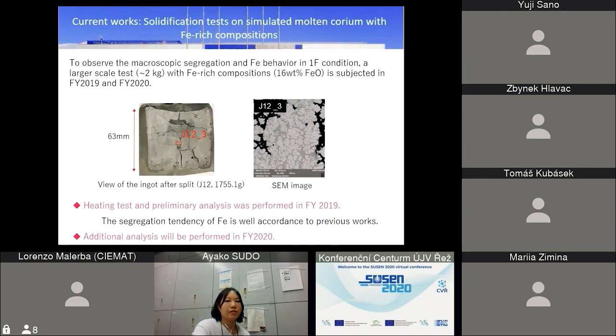Okay, next I will introduce current work: a solidification test on simulated molten corium with iron-rich compositions. To observe the macroscopic segregation and Fe behavior in a realistic condition, a larger scale test with a mass of 2 kg with iron-rich composition was conducted in 2019 and this year. Heating test and preliminary analysis were performed in 2019.